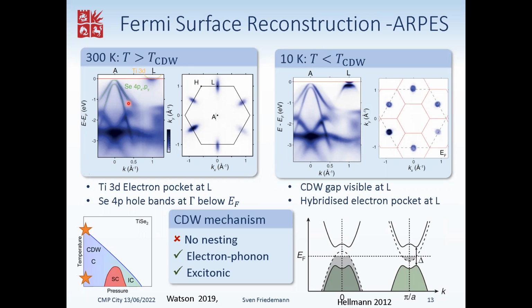By melting the charge density wave with a short laser pulse and then looking at how it reestablishes itself, one can see whether that's femtoseconds, possible for electronic mechanisms like excitons, or whether it's picoseconds, which you would associate with electron-phonon. And both are present and have been observed in several experiments. Hence the association is that both electron-phonon and excitonic mechanisms contribute to the charge density wave here.